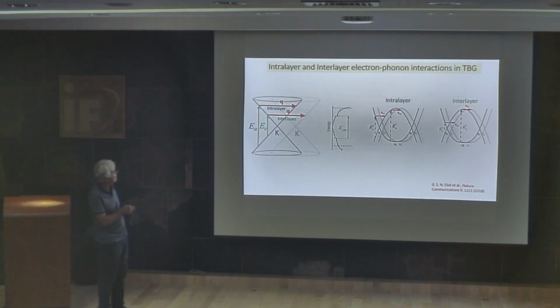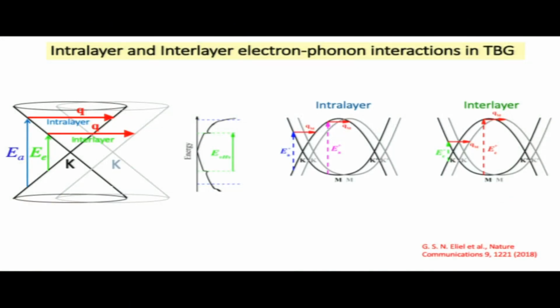But in one case, the electron is scattered from one point in the Dirac cone to another point in the Dirac cone of the same layer. You see here the same cone, from black to black. That's called the intra-layer process. But we could also see that we can have a process that connects the electron from the Dirac cone of one layer to the Dirac cone of the other layer. This was the interlayer process.